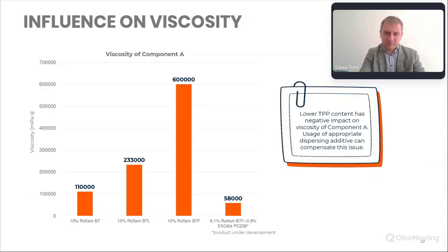Okay, so we have products with low and very low TPP content, but unfortunately, as I also said in the beginning, TPP is very important in terms of application properties, because TPP is the most effective plasticizer. So if we decrease the content of this molecule inside the whole mixture, we also decrease its efficiency. We can clearly observe it in the influence on the viscosity of component A. For Roflam B7L we have doubled viscosity, and for Roflam B7F even 6 times higher than the original Roflam B7.